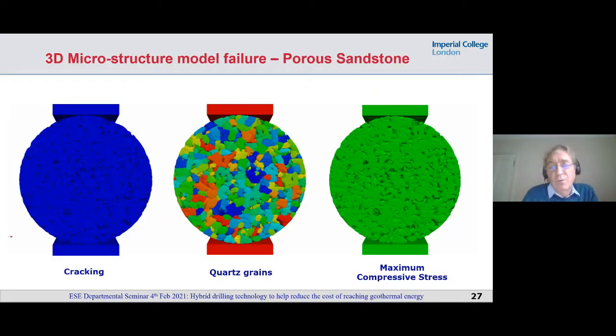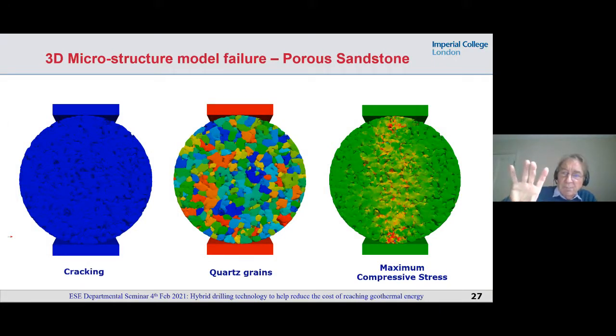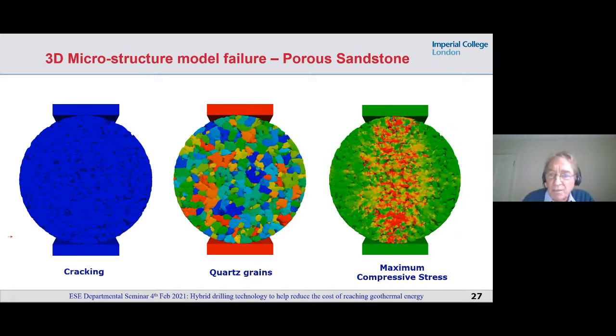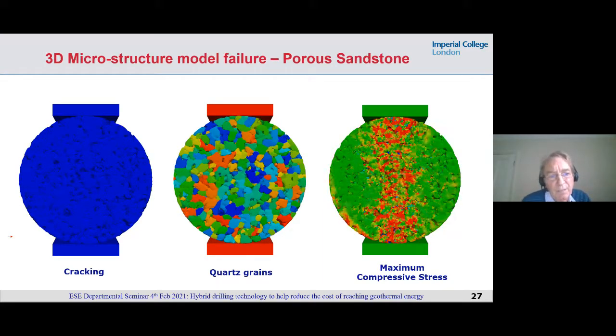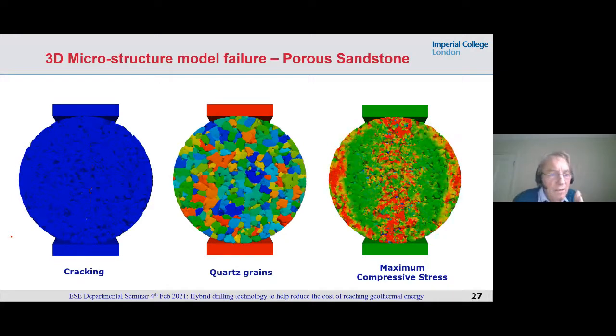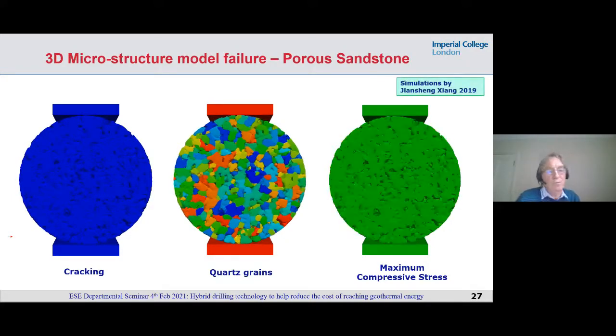So in fact, if we now look at the 3D work we've done, we can see this nice example of a 3D Brazilian disc test. This is the work by Jiansheng Xiang, and on the left-hand simulation you'll see the cracking breaking through from the middle to the front surface. And on the right-hand side, I'll just show you the maximum compressive stress building up. As you can see, the platens are being applied, the displacements are being applied now, and the stresses are building up. You can see an expression of that compression in the front face. Now, if you turn your sight to the left-hand figure, you can see those deep red cracks growing and breaking through to the front surface. And we'll just see that one more time, I think.